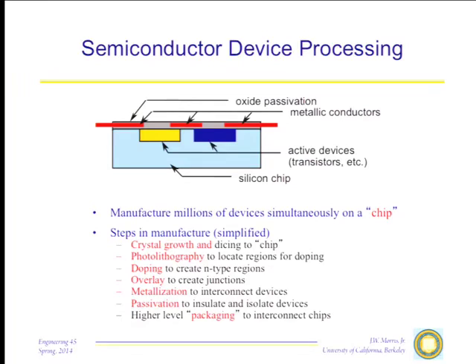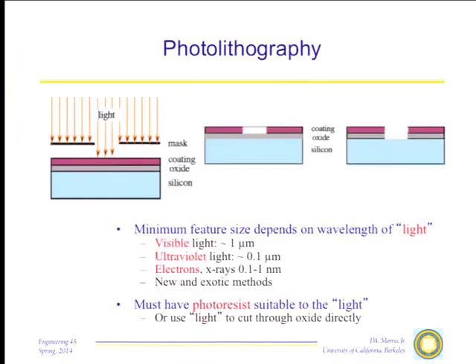There are really several steps in manufacture of a device of this sort. The first thing we have to worry about is the chip itself, the single crystal of silicon, which, remember, has to be very high purity and virtually defect-free, because if it was not, we would not be able to control the properties of the silicon by doping. We then use photolithography to locate the regions we're going to dope. We then dope, that is, add the electrically active solutes. We then overlay to create junctions, these metallic junctions between them. We metallize to interconnect those various devices, put down metallic conductors. We then do what's called passivating, which is essentially just depositing oxides to insulate and isolate the devices. We'll then take a number of these devices and join them together in higher level packaging to interconnect these various chips. So let's just go through this step by step.